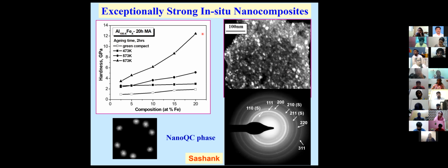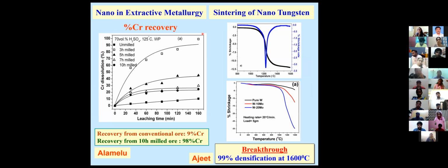Aluminum usually is very soft. You can take an aluminum rod and bend it with your own hands. Okay, it has a strength of 50 megapascal. I'm talking of a strength which is almost about 5,000 megapascal or 5 gigapascal. These are all possible just by making some particles very small. So the strength can be significantly improved. You can do a variety of things.